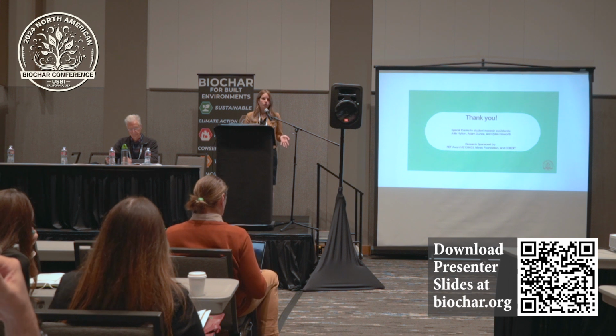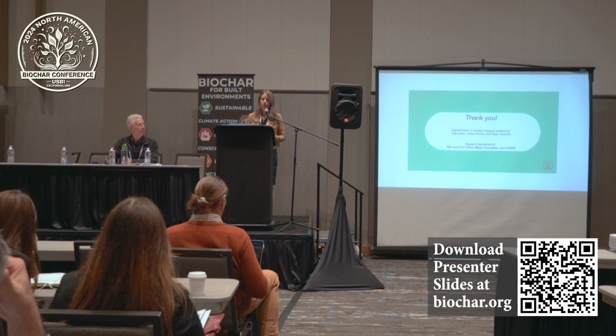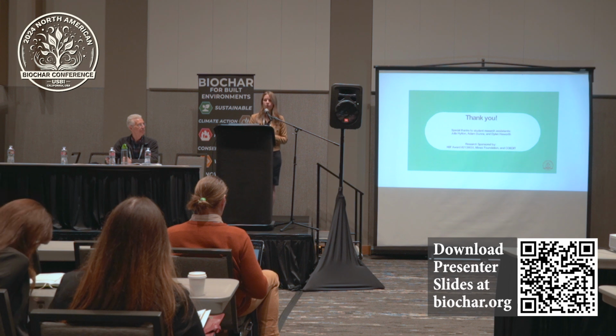So we have not controlled for particle size distribution. We have just been using what we get after the 5 minutes of milling. We did test all the particle size distributions, and that'll be in that publication as well if you're interested. But it's a fairly tight distribution, and it's all below the cement powder. So that's typically what we want, so that you don't have these big inclusions that are affecting the strength.